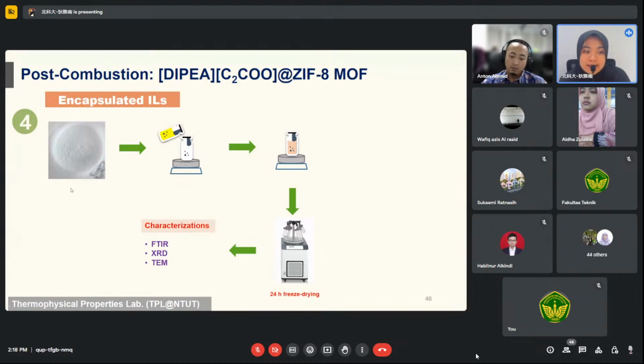So we use the pristine ZIF8 and we combine it with ethanol and the ionic liquids. We need a little help from the ethanol, not that much. So what's the function of ethanol here? To reduce the viscosity of the ionic liquids, because this ionic liquid is a little bit viscous. If you use a viscous liquid and then this is powder, your encapsulation process is not that good.